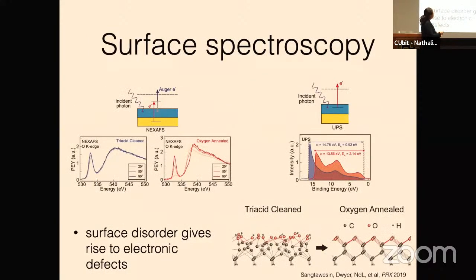Okay, so that's from the point of view of the NV center, and then we can look at the surface spectroscopy. If we look at this X-ray absorption spectroscopy at the oxygen edge, sort of to my disappointment, these things look broadly similar. I think surface scientists hate it when I put it this way, but I have a peaky thing here and a shoulder thing here, and it's essentially the same here. But the drastic difference is that if I do a polarization dependence, you can see that it's completely washed out for this acid clean sample, whereas the oxygen annealing gives you this huge change in intensity as I change the polarization. So the general picture is that these things are chemically quite similar, but there's a much higher degree of disorder before you do this last step.